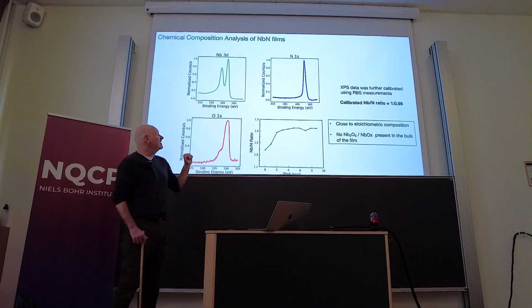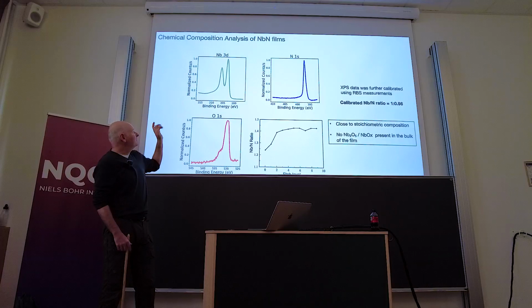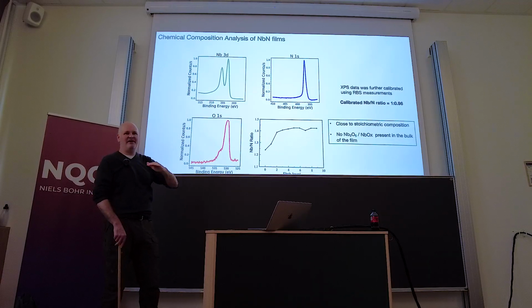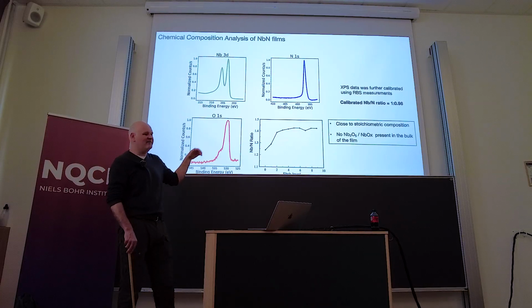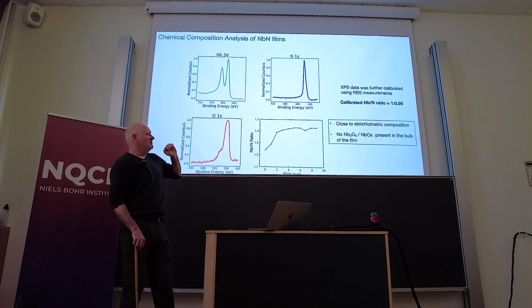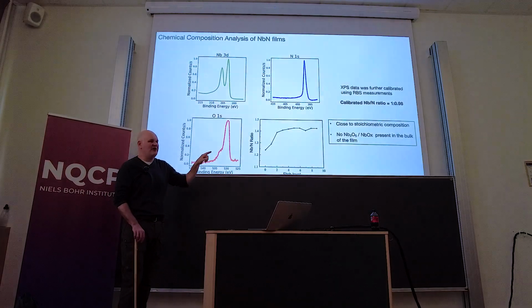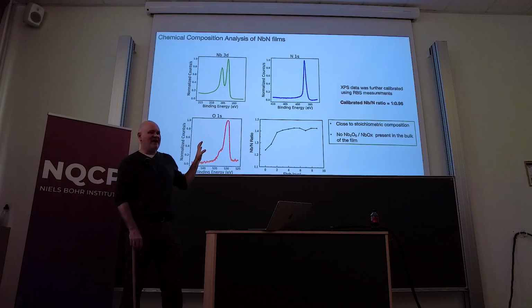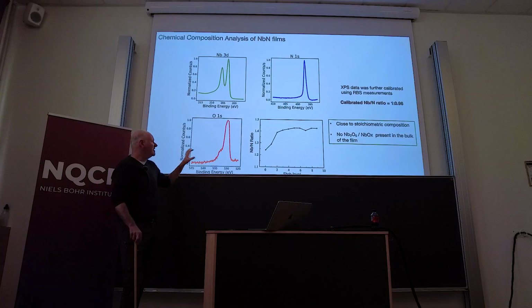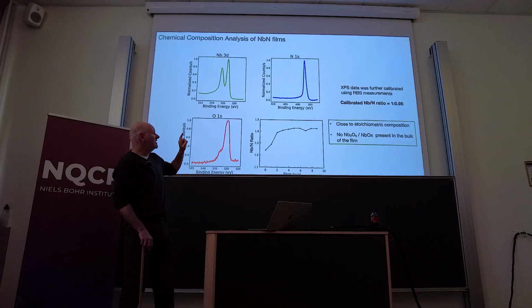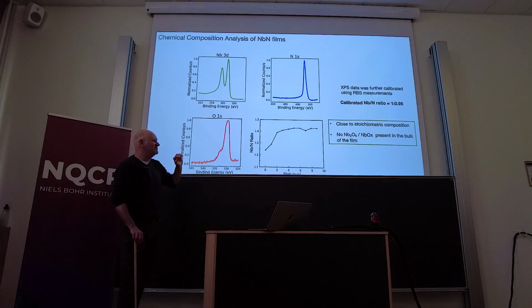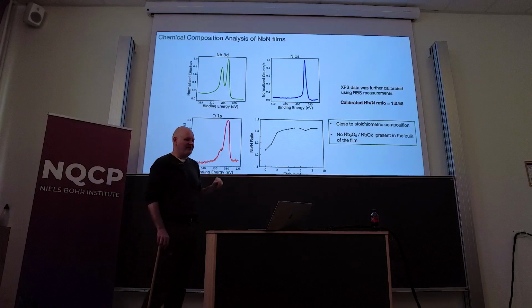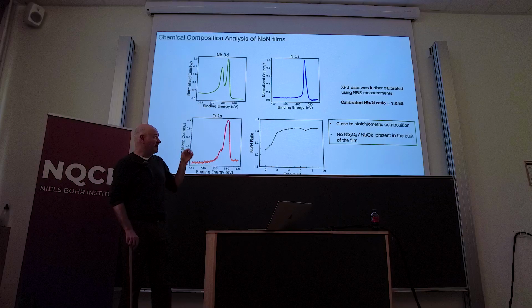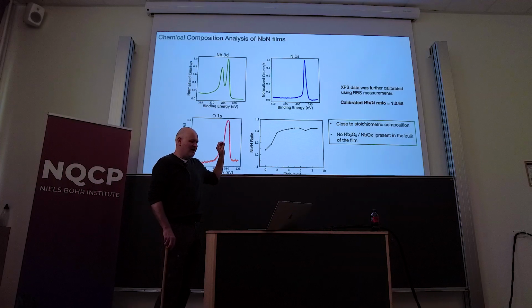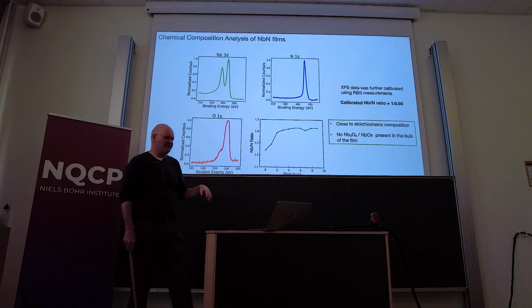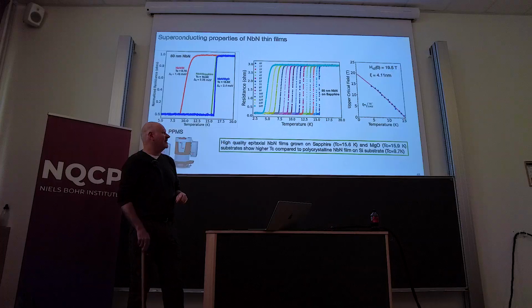So this is XPS data taken on these niobium nitride samples. The XPS spectra that you're seeing here are actually milled down a little bit into the material because these were not protected from the air, so they're slightly oxidized. But once you get down into the material, we do see oxygen, but we don't see any Nb2O5 or NbOx. And we think this is because this is not a UHV XPS system, so there is oxygen in the system. So we always get a little bit of oxygen on the surfaces. But essentially, the ratio of niobium to nitrogen is essentially 1-to-1 once you get down into the film a few nanometers, which is good. It's what we expect. And in order to get this, we used Rutherford backscattering to confirm the concentrations, because you really have to do that to understand analytically what you have.